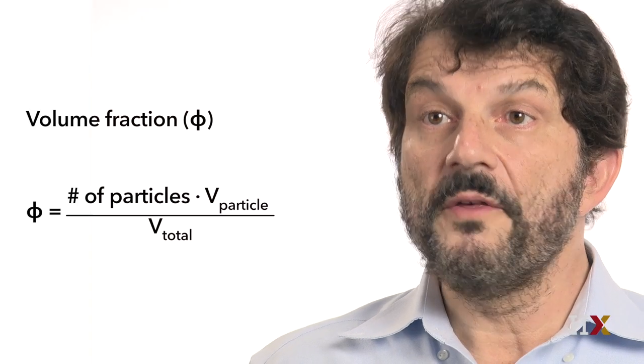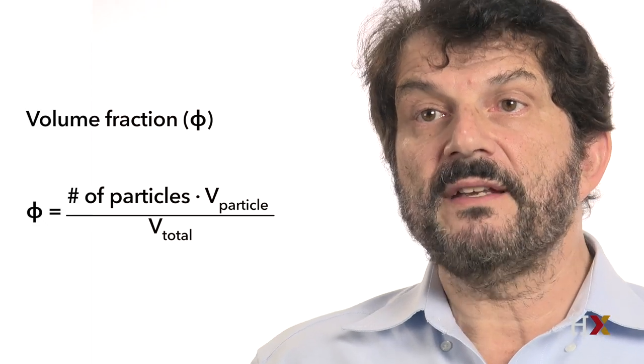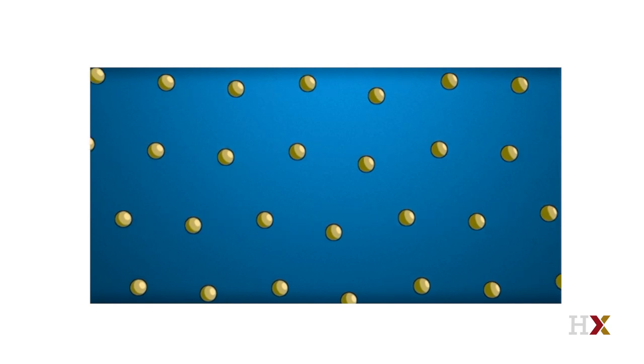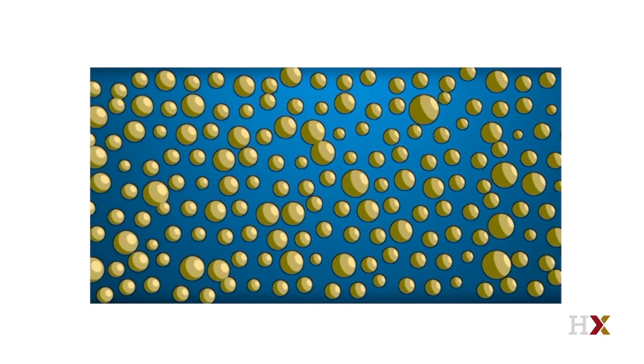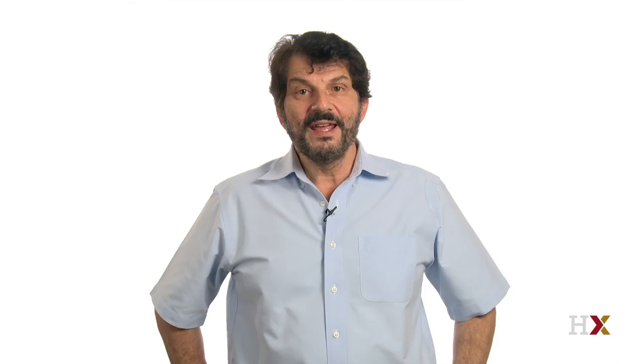When there are very few particles in the fluid, or their volume fraction is very low, they have almost no effect at all — the particles just flow with the fluid. However, when the volume fraction of the particles increases, they become crowded. It's more difficult for the particles to flow over one another; they collide and move on top of each other, taking up more volume and restricting flow. This really impacts the flow of the fluid and increases its viscosity. For that to happen, the volume fraction has to be quite high — sufficiently high that the particles can't easily flow over one another, which doesn't happen unless the volume fraction gets to be on the order of 50%, where half the volume of the fluid is occupied by the particles.